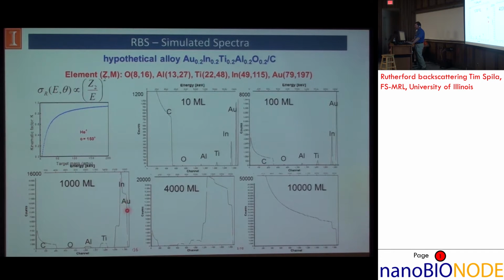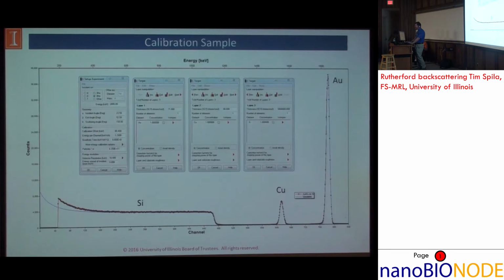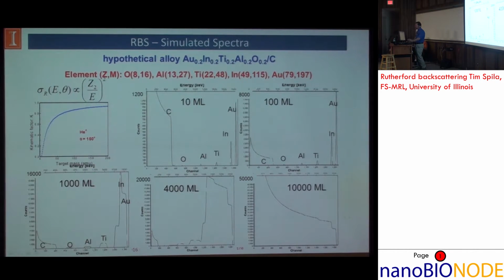And the indium and gold were close enough together that they're now starting to overlap. So you can just think of this as a sum of the indium plus the gold for the counts in that one region. So it's just a simple sum. As you go thicker and thicker to 4,000, you have more and more things that are starting to overlap. And eventually when you get really, really thick, then everything just mushes together and you no longer have that sensitivity.